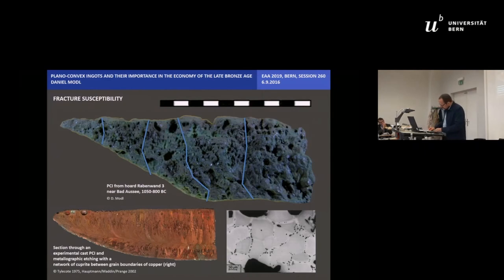Other factors that facilitate the partition but cannot be explained here in detail are the chemical composition, especially a higher content of elements such as arsenic or iron as well as microscopic impurities along the crystal or grain boundaries like cuprite or copper sulfide inclusions. These factors can dramatically deteriorate the mechanical properties of the copper and make it brittle.